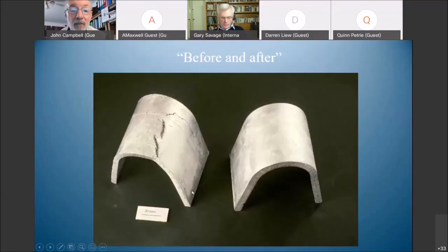And this one where we made a small casting. This is about a 100 by 200 length, a simple bit of slab casting. This is in pure aluminium. And this is done at the right speed where there was no entrainment. This is done where there was some entrainment.